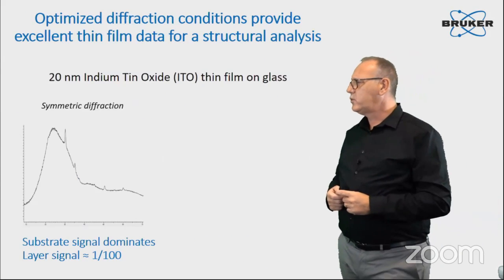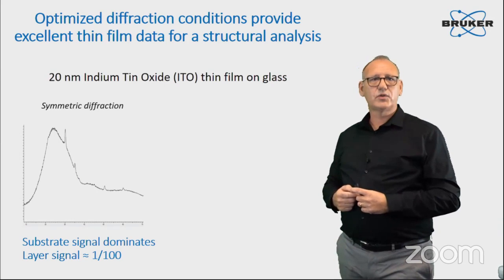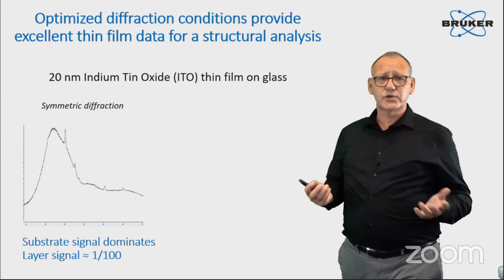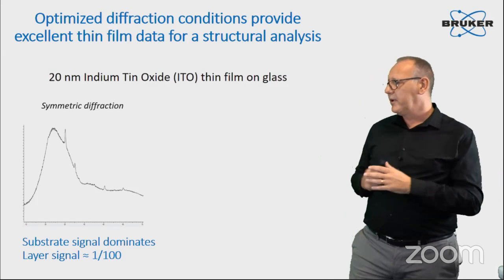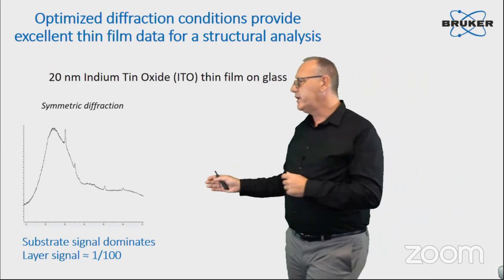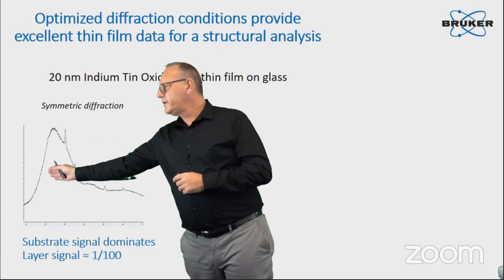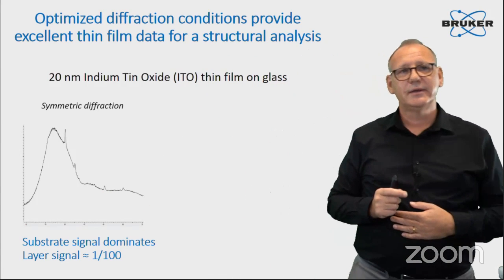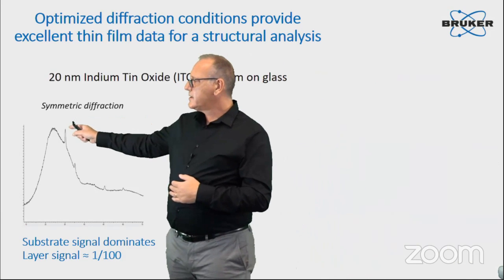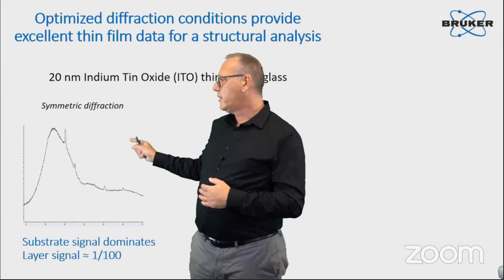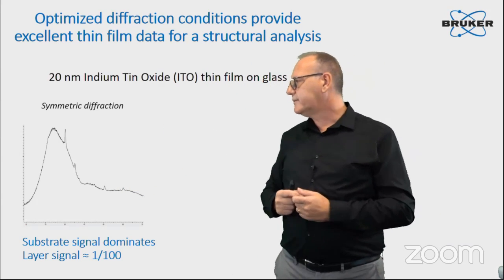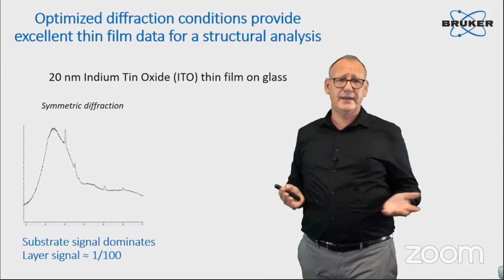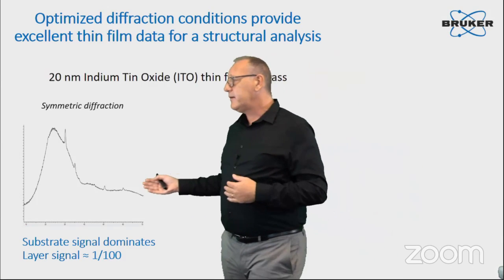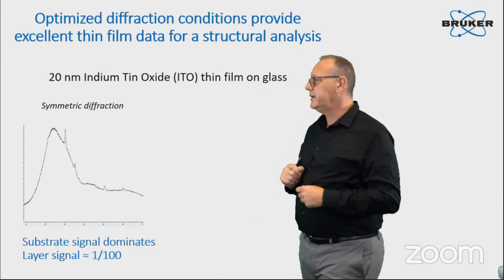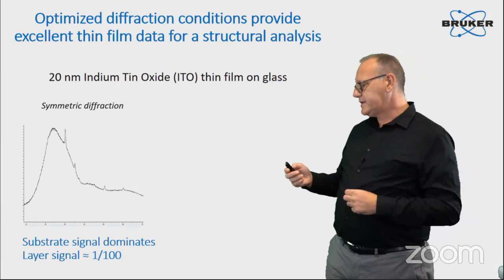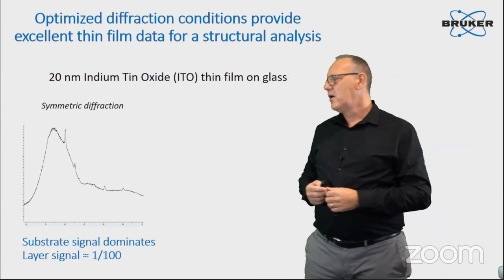This is an example of a 20 nanometer indium tin oxide thin film on top of glass. If you measure it like you would measure a powder sample, you end up with a tremendous contribution, those big, large humps here, of the amorphous glass substrate. And on top of it, you see a few peaks that most probably come from the top indium oxide 20 nanometer layer. But the layer signal is in a range of less than 1%. So, well, you could say, I'm happy I have 4 peaks from indium tin oxide, so most probably indium tin oxide is in, but you cannot do much more. You cannot really analyze the structure of the layer.